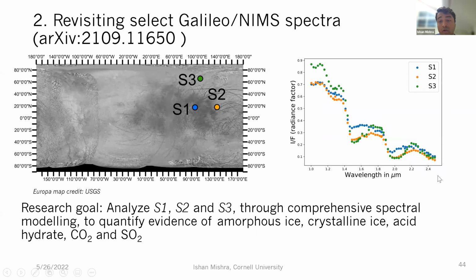So the data was within 1 to 2.5 microns, where most of the Galileo data resides, because beyond, even though the spectrometer extended till 5 microns, the data is very noisy and it's mostly unusable. So our goal was to try to do a spectral fitting analysis of the spectrum using 5 components. So the 2 forms of water ice is obvious, because water ice is a bulk component everywhere on Europa.